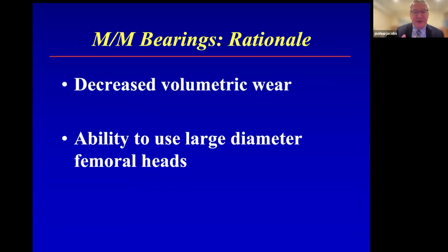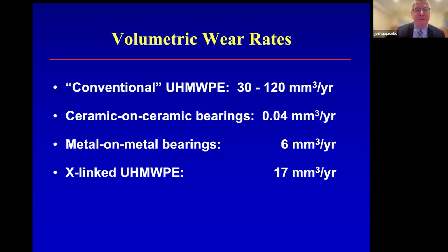And also because of the mechanical properties of metal implants, we could put a far thinner acetabular component. We have to have a certain thickness of a polyethylene acetabular component or it'll wear through. But for metal, which is far more wear resistant than polyethylene, we can make a much thinner acetabular component so the femoral head can be larger, and that would make the hip more stable. It wouldn't dislocate. By using larger diameter femoral heads, the hip was much less likely to dislocate, which is also one of the failure mechanisms of total hip replacement that was common at the time.